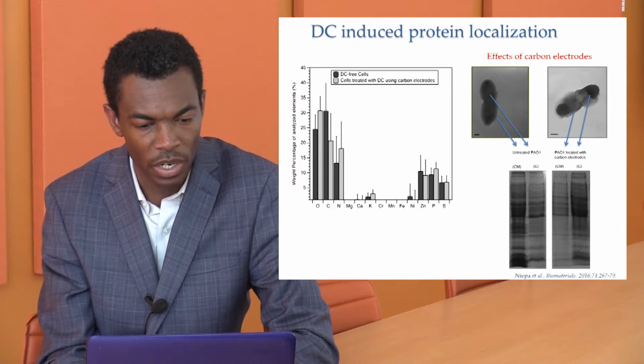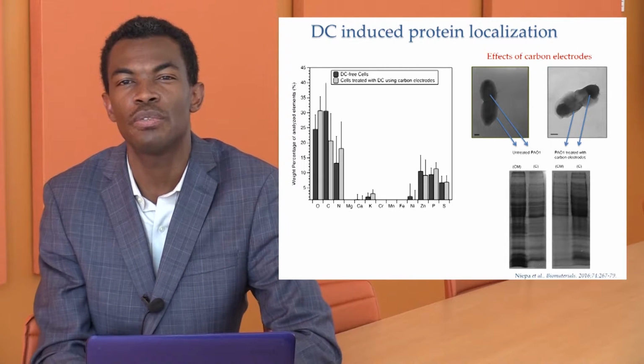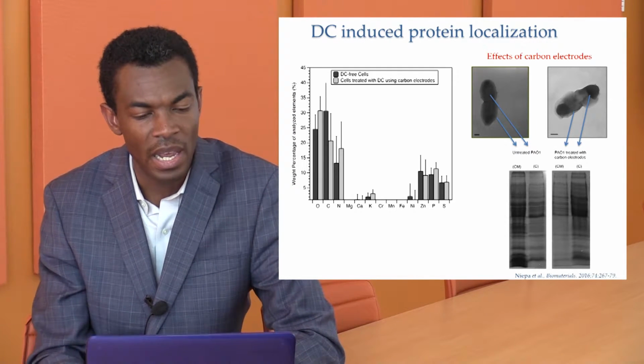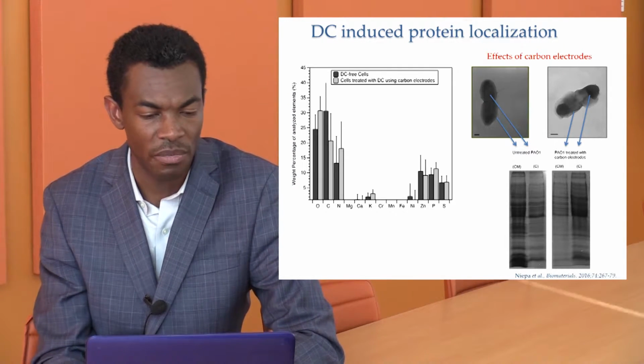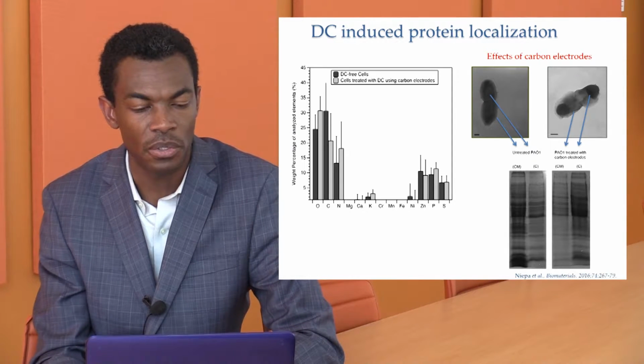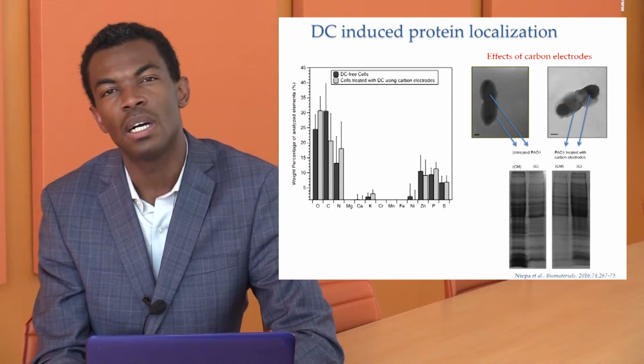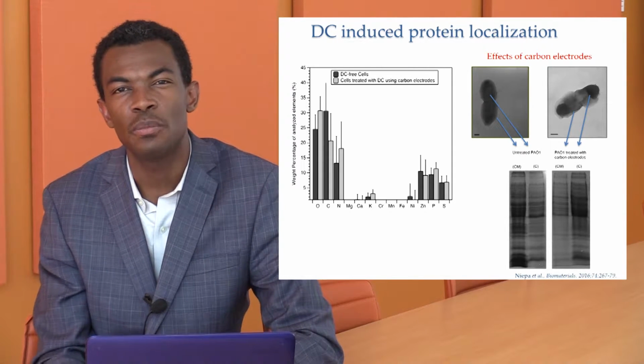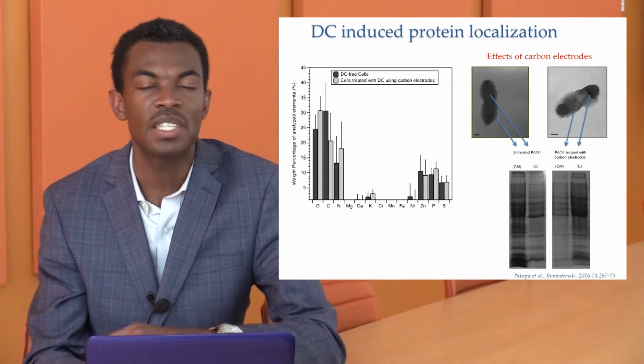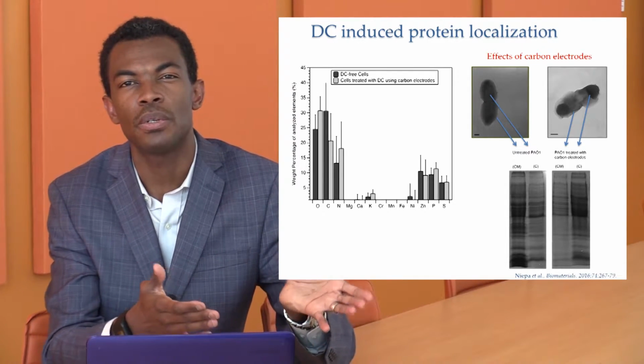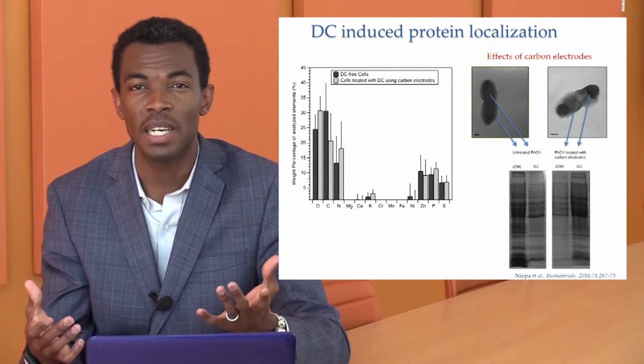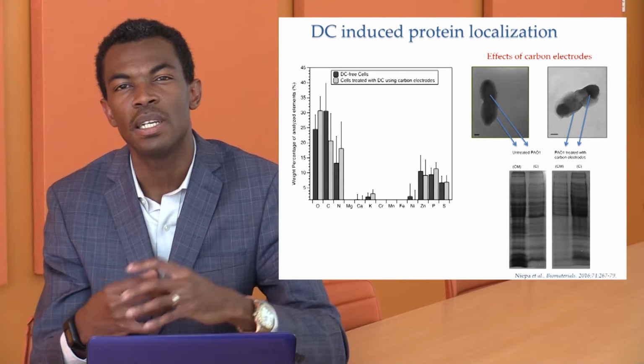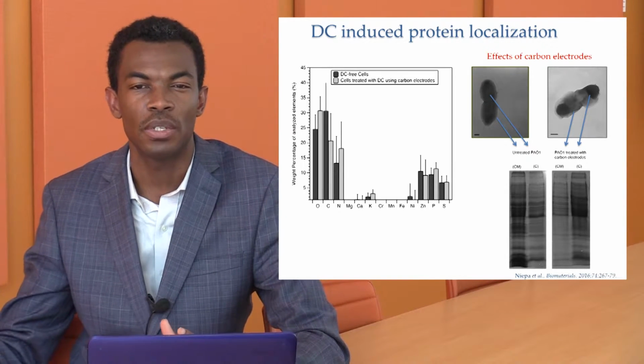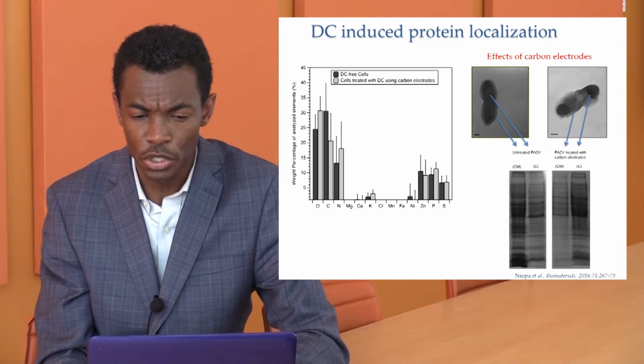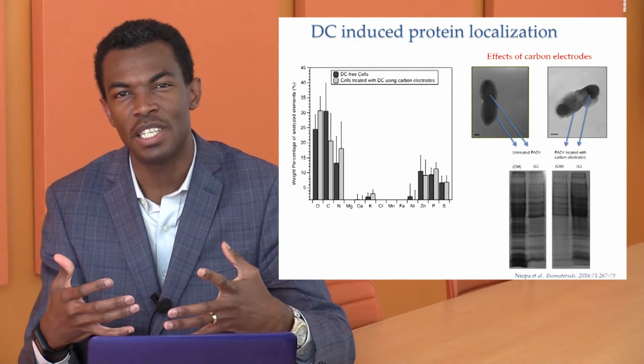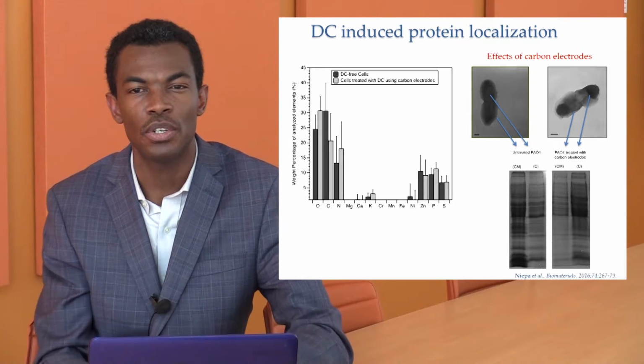And as we can see in this graph, there's no significance in the difference of those different chemical elements that we're trying to identify, whether oxygen, carbon, or nitrogen. All these chemical elements seem to have the same concentration in cells treated with carbon versus untreated cells, which means that most of the things that were accumulated inside the cell was not an external carbon that we're bringing up. So it looked like the treatment caused so much stress to the cells that they reorganize the inside.